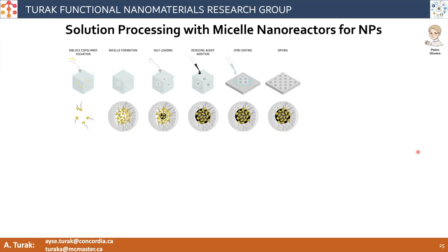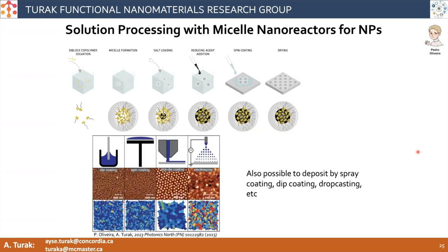And though most of the arrays I showed are from spin coating, it's actually quite agnostic to the technique. So it's possible to use dip coating. I apologize for the glare, if it's not so obvious, but you can see there's a similar size dispersity, and even the packing is quite good. The dip coating, the spin coating, the slot die coating, or light spray, not so great, but you can still spray something. And whether it forms an organized array is still up in the air, but we can still tune those properties.